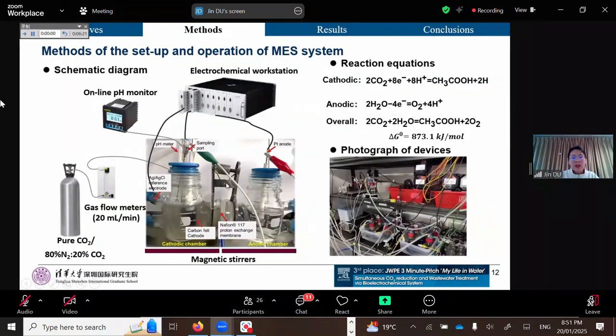Here is a photo of our experimental setup. Microbial electrosynthesis was conducted in a dual-chamber reactor. The carbon felt acted as the cathode, the platinum sheet acted as the anode, and the cathode potential was controlled at -1 volt versus the reference electrode.